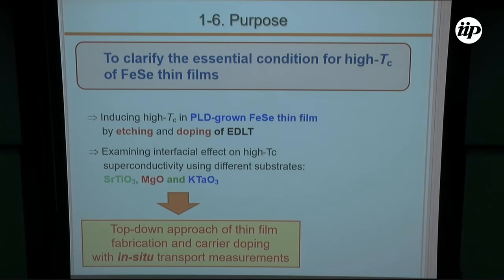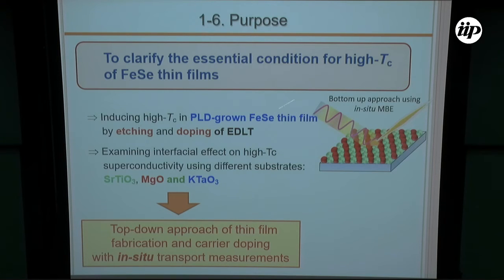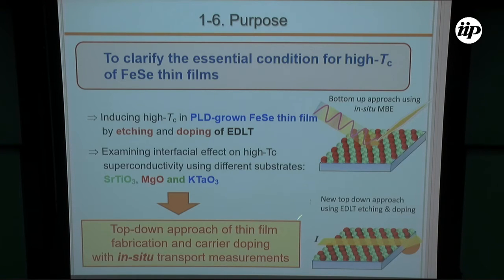Usually, the physics of very thin films has been studied by using the bottom-up method like in-situ MBE. But in this work, we address this same subject using an alternative top-down method, using the EDLT. The advantage of this method is that we can do the thin film fabrication and carrier doping in one sample, with in-situ transport measurement with decreasing thickness.